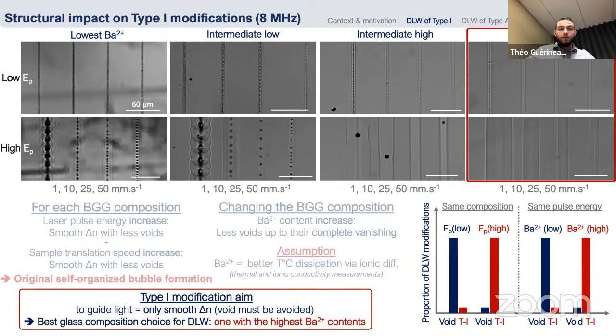As I told you earlier, as the main aim of the type 1 modification is to guide light, we only want a smooth delta N. And so that's why we must avoid the formation of these bubbles. In this case, by just tailoring the glass composition, we can avoid this type of bubbles, and so we will go preferentially to the glasses with high concentration of barium.